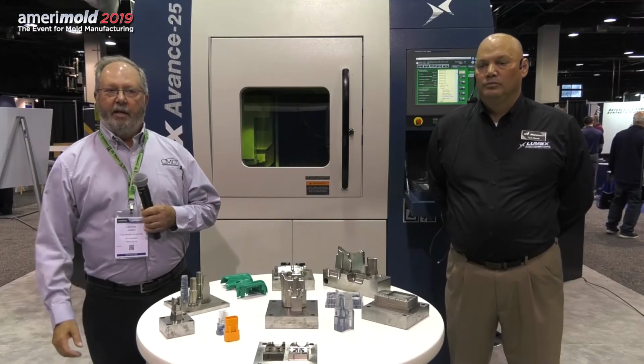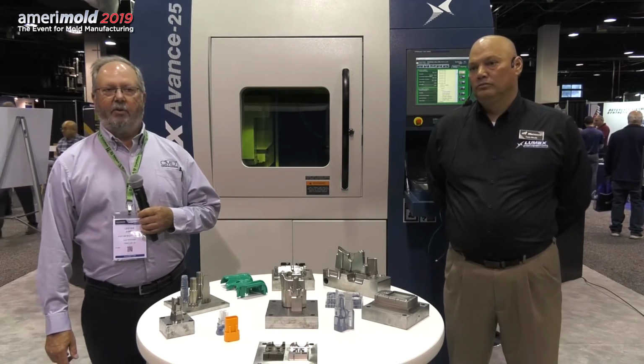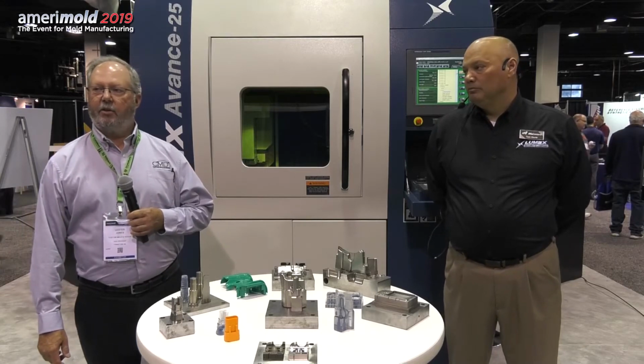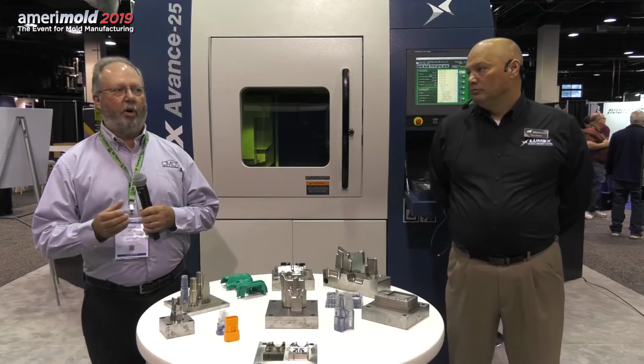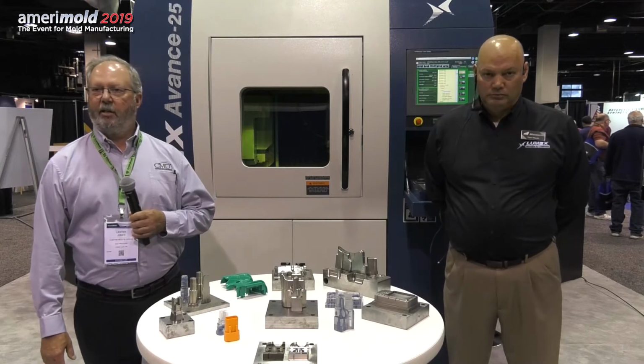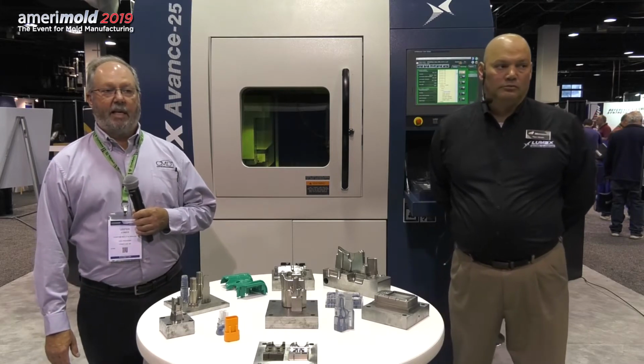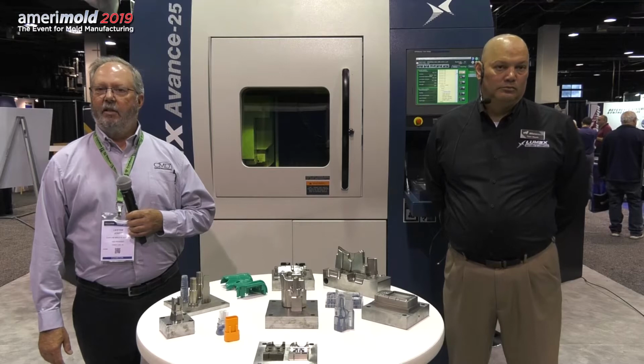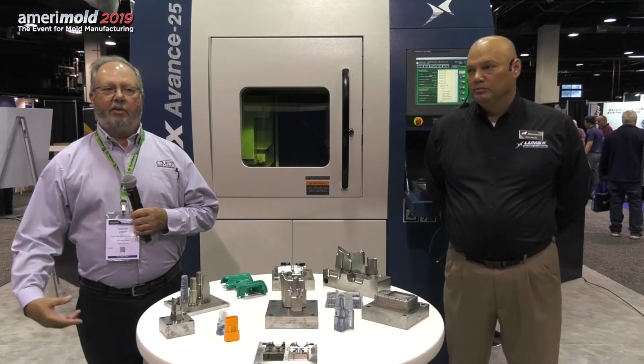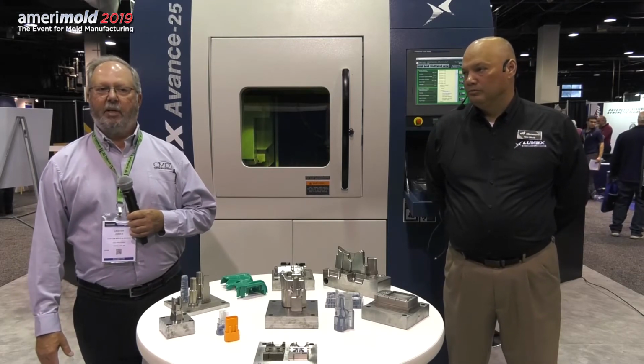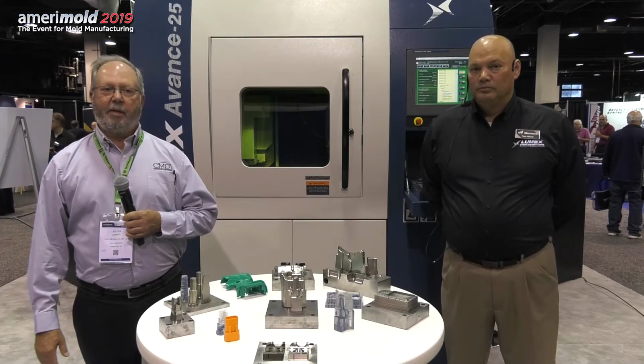of conformal cooling. In this particular study, we were able to take a part that had an 18-second cooling time and reduce that down to 10 seconds. So we took 8 seconds out of the cooling time cycle and actually improved the warp condition in the part. So we actually ended up making a better part and saved 8 seconds for every cycle. And through our calculations with the cost structures that we have in place, in about 85,000 pieces, we'd have that new core paid for. So it demonstrates the opportunity to really save some money and make those parts a lot more economical.